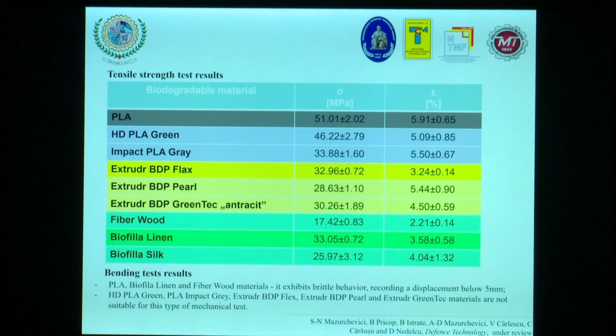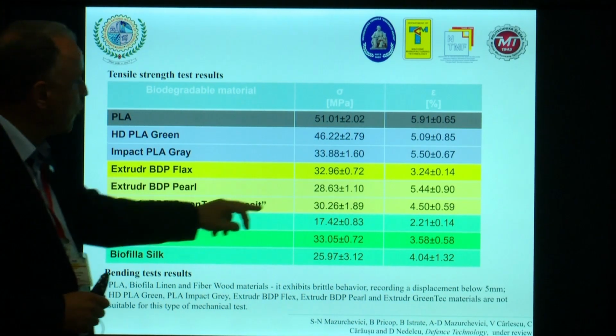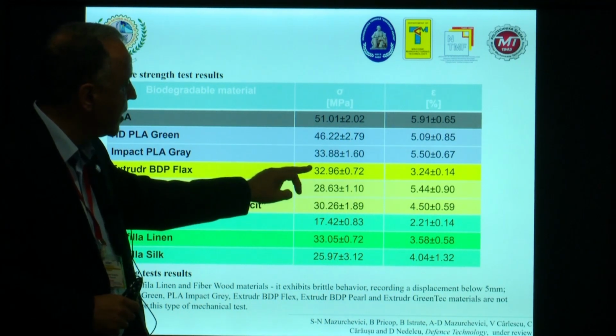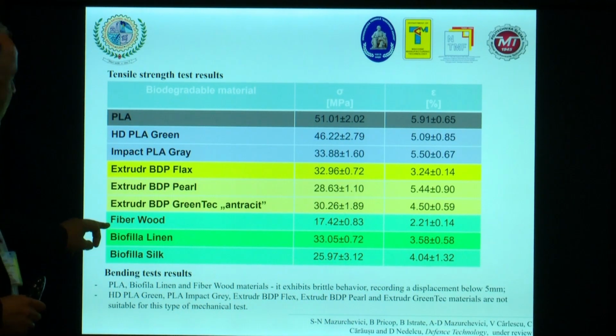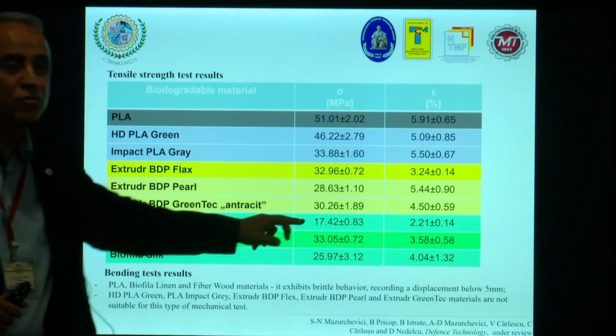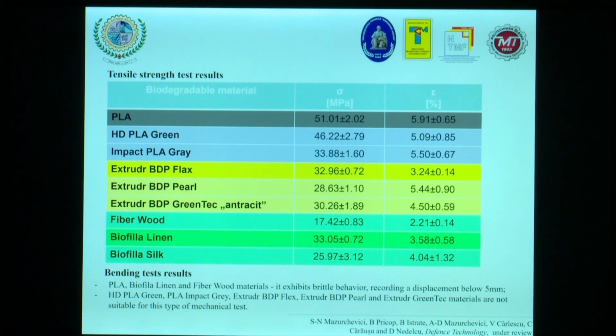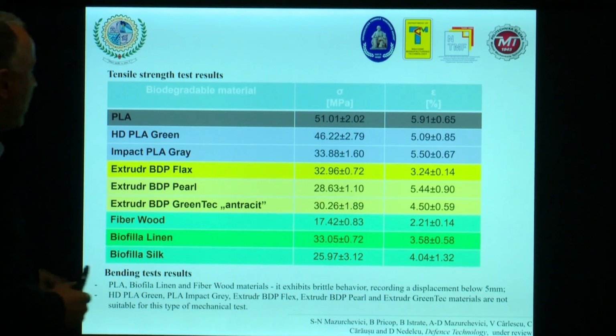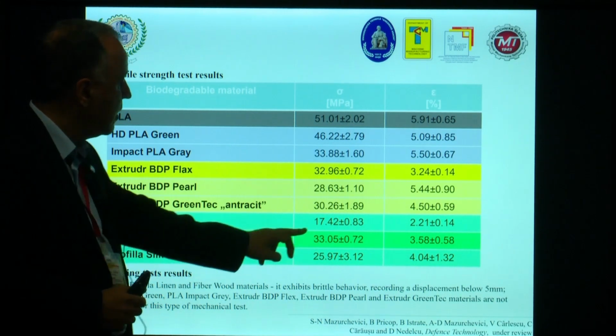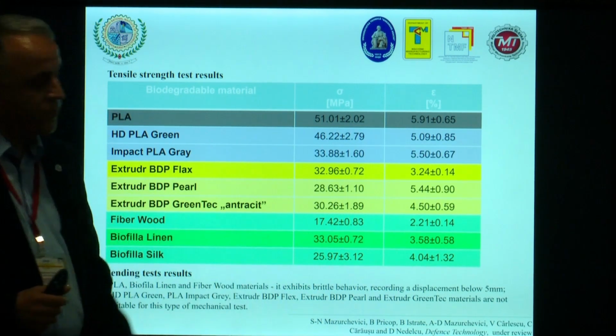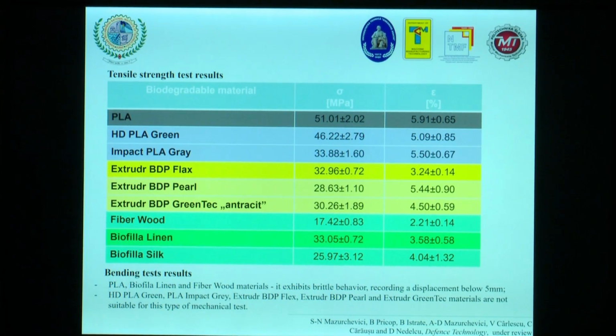High density PLA, around 46, impact PLA, 33, Extrudr, you can see the Extrudr group, from 28 megapascal to 32. Fiberwood, not so good, but very good surface quality. Biofila linen and silk from 25 up to 33 megapascal.